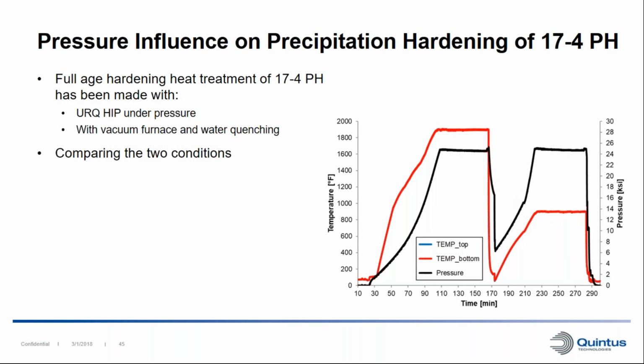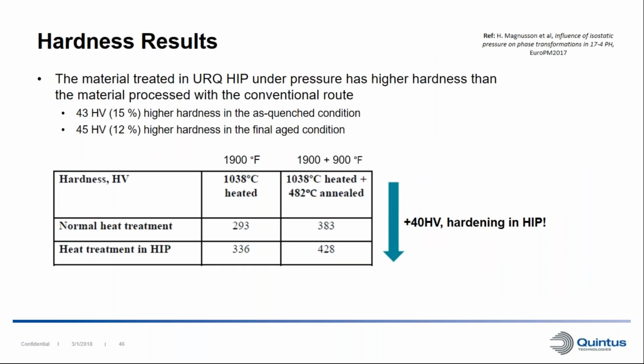Another study that we made together with Swerea KIMAB in Sweden was to perform the full age hardening cycle of 17-4 PH in the HIP and compare it with the same material processed in the conventional way, in a vacuum furnace with water quenching. What was quite interesting is that the material processed in the conventional way got a certain hardness in the quench state and in the final age hardened state. However, the same process performed in the HIP under pressure actually gave higher hardness both in the as-quenched condition and in the final condition.